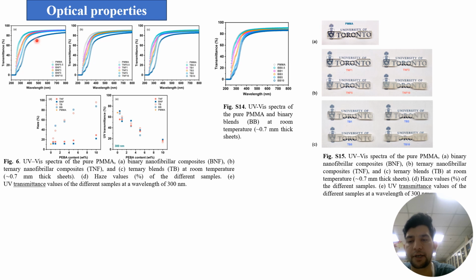When the PEBA nanofiber content was increased up to 5 and 10%, the light transmittance value dropped to around 85 and 80 respectively, in both the binary and the ternary blend systems. This decrease is mainly attributed to an increase in the entanglement degree of the nanofibers at higher concentration. Figure 6c and figure S14 also exhibit a high level of light transmittance comparable to that of the nanofiber composite.